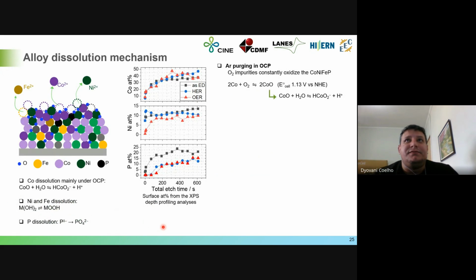So, what is happening with the catalyst? The cobalt dissolution mainly occurs during the open circuit potential due to this instability of the cobalt oxide. In alkaline medium, the cobalt oxide is dissolved by the production of cobaltite. The nickel and iron can be dissolved because of the instability of the metallic oxide, the iron and nickel oxide, producing the oxide hydroxide, which is the active site for the oxygen evolution reaction. But when this catalyst is kept at open circuit potential, this oxide hydroxide is not stable, so it produces the oxide layer, and this change in the structure promotes the catalyst dissolution.